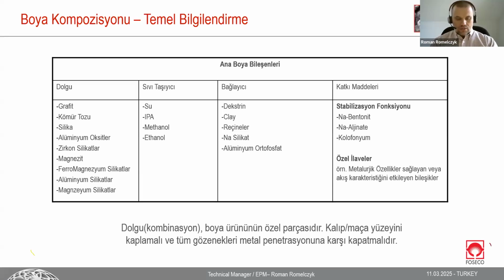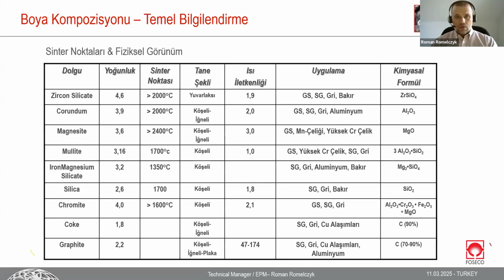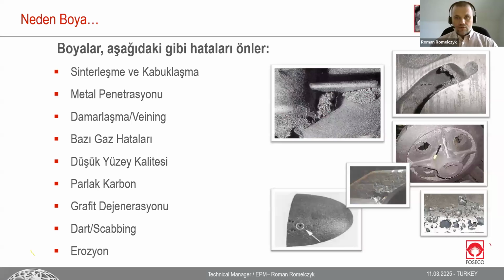So this is the composition of the coating, and the big question is what we use a coating for, why we use coatings. When we talk about defects, the coating itself cannot cover the mistakes of mold or core preparation, but it can help and support the surface finish. Problems like burning, metal penetration, and veining, for which there is a special group of coatings with anti-veining properties. Also some gas defects, lustrous carbon, and more. Even some kind of scabbing, not exactly filtration.